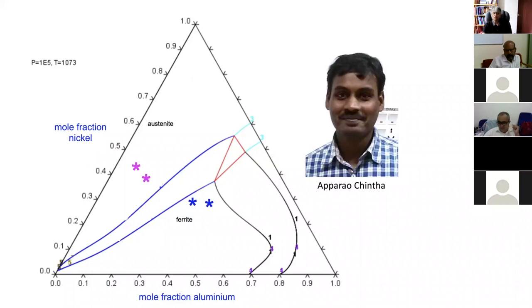So the next calculations that he's going to do is to introduce other elements. So we have the aluminium, iron, and nickel already in this diagram. Now, supposing I add chromium, why doesn't the structure actually look different? Okay, so we want to find out, using just plain thermodynamics, why we are getting these crystal structures. Okay, and at what temperature should we calculate the isothermal section of the phase diagram so that everything falls into place? Because obviously these isothermal sections change with temperature. So very simple analysis. Now, another design method that you can use for high entropy alloys is machine learning.